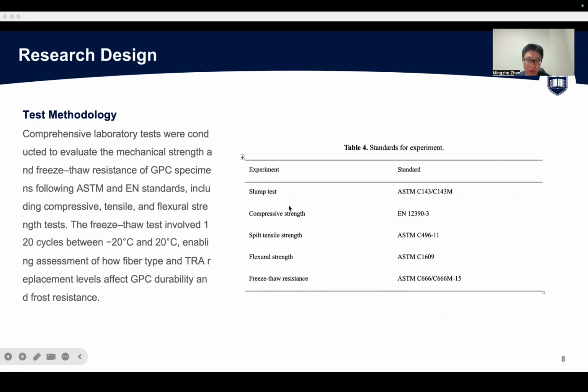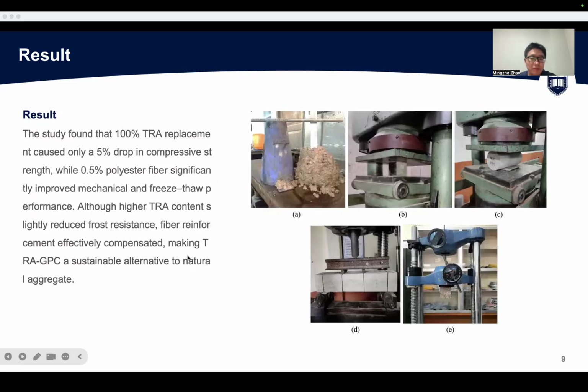The experiments include the slump test, compressive strength, splitting tensile strength, flexural strength, and freeze and thaw resistance. The freeze and thaw test involves 120 cycles between -20 and 20 degrees, allowing elaborate assessment of how fiber type and the TRA replacement levels affect GPC durability and frost resistance.